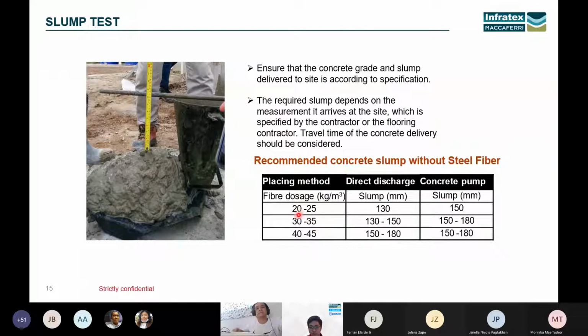Then for fiber dosage between 30 to 35 kilograms per cubic meter, the slump when pouring by direct discharge must be within 130 to 150 mm, while when using a concrete pump, it should be 150 to 180 mm. Then last, for fiber dosage between 40 to 45, both for direct discharge and when using a concrete pump, the slump must be 150 to 180 mm.